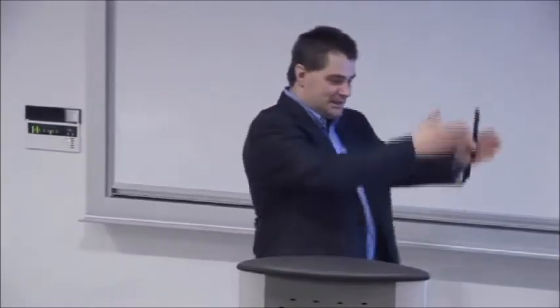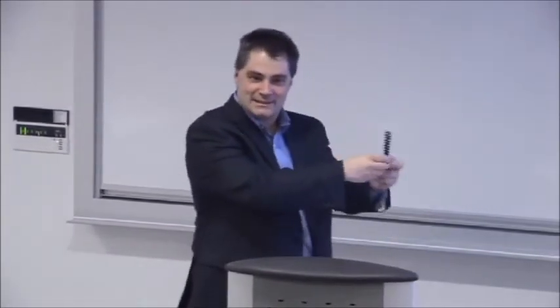That's why we also did work to try to divide these graphene flakes in stripes, to cut them to increase the defects at the edge, to study them, understand them a little more, also with the objective to try to discriminate the effects that are related to defects in the fabric of graphene, like vacancies, and defects at the edges. So I will skip this.